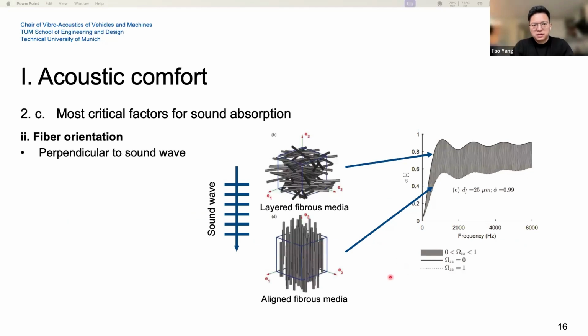The next factor is the fiber orientation. In these two geometries, you can see that in one the sound wave is perpendicular to the fiber orientation, but in the other the sound wave is aligned, parallel to the fiber direction. The first one obviously has a much bigger tortuosity, so the sound wave has to penetrate through randomly connected pores. But for the aligned fibrous media, the sound wave just goes through the media. There's no such random or complicated pore connection. And they showed a very big difference in sound absorption.